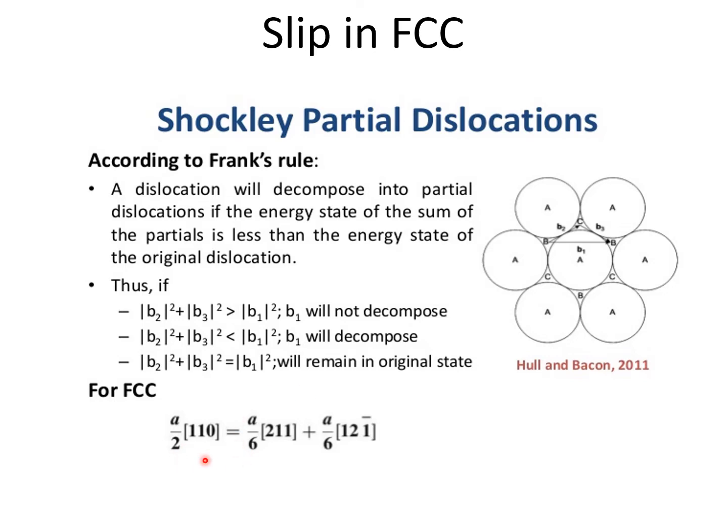So in order to move the lattice and get it back into its original configuration, a perfect lattice, it actually takes 2 steps. If we only use 1 step, the lattice is now in a quasi, if you like, crystalline state. It's not FCC anymore, because by moving that from B to C in this particular instance, that would create what's called a stacking fault on this layer.